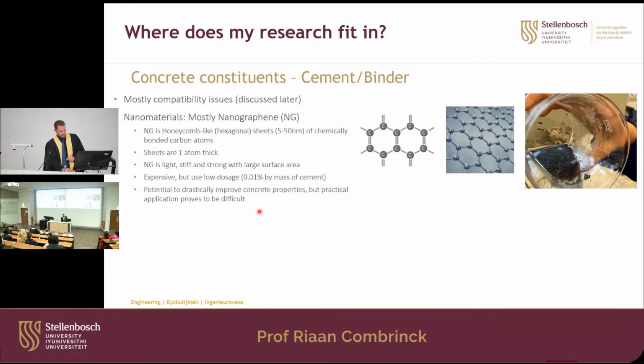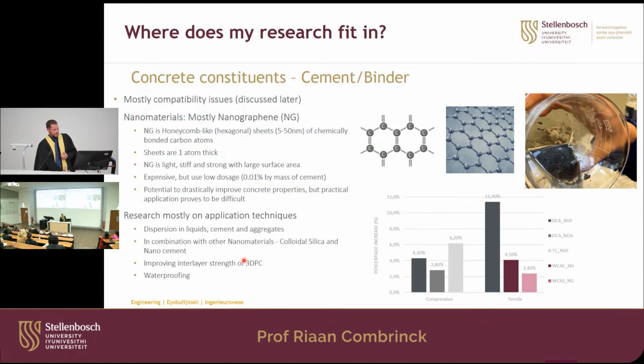So what we've done so far is mostly research on application techniques. We've been dispersing it in liquids, in the cement, also coating aggregates. We've been using it in combination with other nanomaterials, colloidal silica, nanocement. We're using it to improve the interlayer between 3D printed concrete and also for waterproofing of concrete. We've had some better results, I think, but some initial results show that we couldn't get the compression strength that much higher. It's because this application technique is so difficult to get right. But for most of them, we've been seeing a big increase in tensile strength. So even if you get the application method wrong, you get the increase in tensile strength as well.